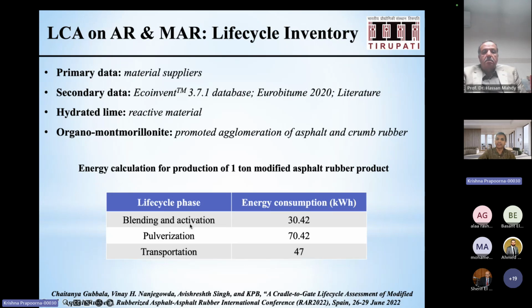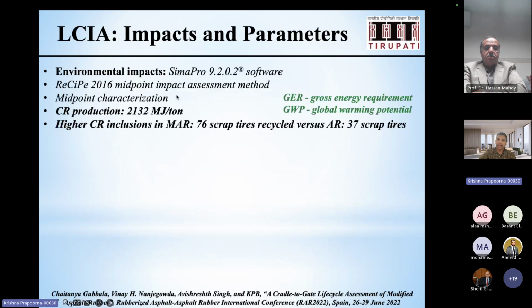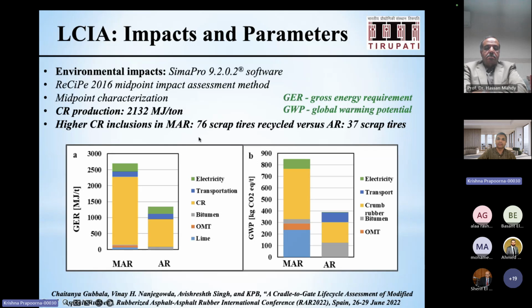So for blending and activation of this modified asphalt rubber, the energy consumption was about 30 kilowatt hours. Pulverization was the largest, obviously, because you have to run it through a process which will bring it to a powdered form, right? And then transportation, which I assume will not be much if you're doing it in your own plant. So basically, when you run it through a software, it'll actually ask for all of these. Now, let's say you create your own LCA package, then you'll see that you don't even need to include the transportation sector, right?